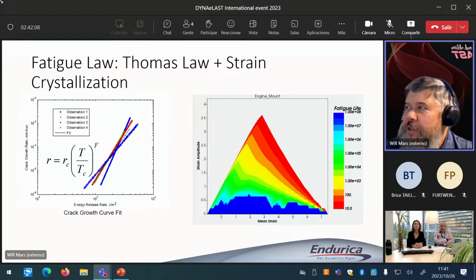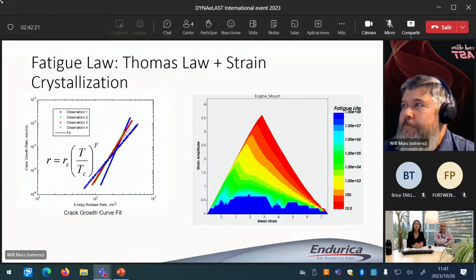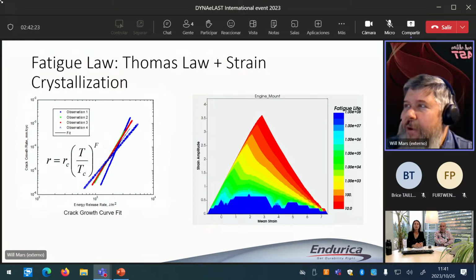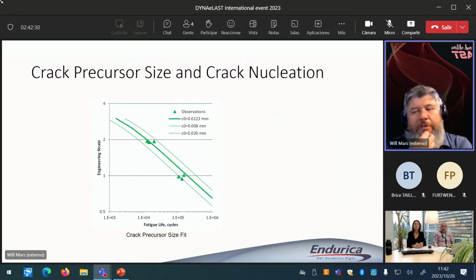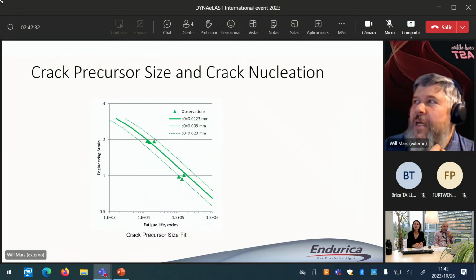And so you could think of this as just a contour plot showing how fatigue life of, let's say, a tension strip depends on mean strain and strain amplitude. In order to define that plot, we would also need to define the crack precursor size. And in order to do that, we will use crack nucleation experiments.